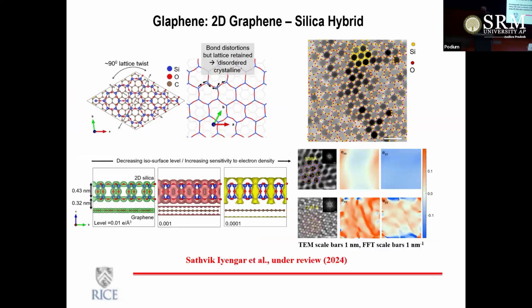So let's say you are able to make 2D silica, and then you take graphene and put them together, and you have a very different kind of architecture. In fact, this combination of graphene and silica, we call it glaphene. And basically, it's a single material because there is electron transfer and there is hybridization between the two layers, right? In fact, we did a lot of experiments.